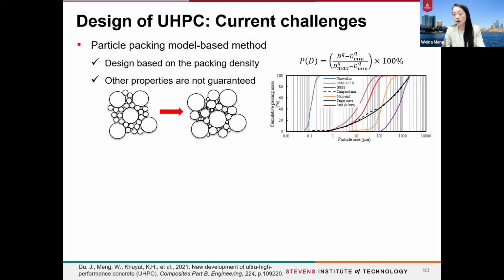So besides the biochar and OSFA, there are actually hundreds of different types of waste materials considered to develop the sustainable UHPC. So here there are really two major ways to design or optimize the UHPC. The first is particle packing model-based methods. This is the model people usually use for high packing density. But this method can help the system to achieve very high particle packing densities, but it does not guarantee the key properties are high performance, such as the tensile properties or the shrinkage or the durability.